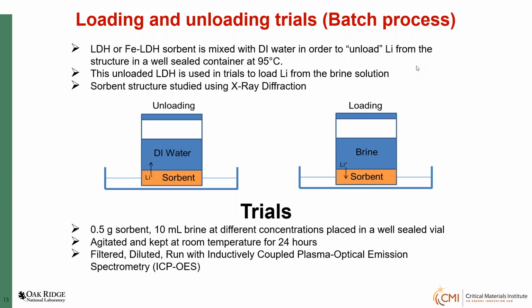We did it on a small lab scale. So we worked on layered double hydroxide, LDH, and iron doped LDH. So we modified it. These are simple trials. You can take water at 95 degrees and do loading and unloading with different sorbents. You can actually run ICP and do a batch process instead of a column.